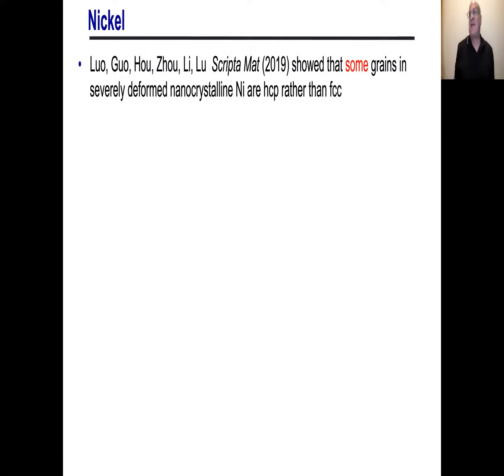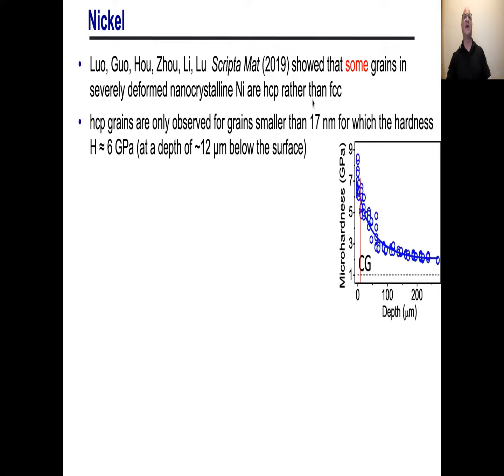Okay, this is my favorite experiment. This is the one that I mentioned. This is from the group in Shenyang. So this is the paper I showed you in the beginning, where you saw that some grains of this polycrystal under this severe plastic deformation that you get, some of the grains transform to HCP rather than stay FCC. And we can do a little bit of analysis on the data they provided in this paper. So they found that some HCP grains are only observed when you've got grain sizes smaller than about 17 nanometers. And so if I look at where the grain size is of order 17 nanometers, it's about 12 microns below the surface. If I read up to 12 microns below the surface, I get a hardness which is about 6 GPa.